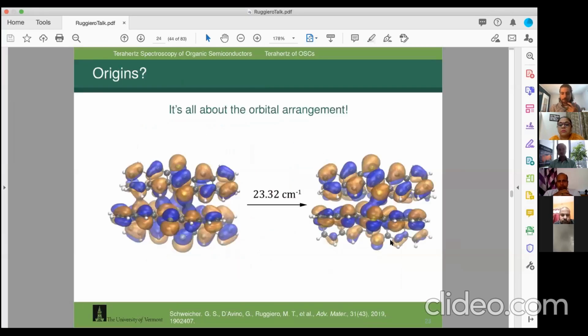So we can look into why, and if we look at the orbitals, what's happening is in the equilibrium position, the orbitals of two adjacent molecules line up in phase. But as you translate the two molecules, that leads to the orbitals lining up out of phase, which effectively traps the free carrier and reduces the ability of the carriers to move through the system.